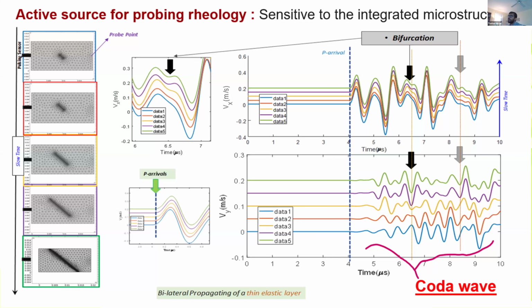So overall, what we're finding is that the active source is really sensitive to the microstructure. It has the potential to being able to actually predict a lot of the stress state, the bulk rheological state of the sample, because it's sensitive to the damage, which is correlated with a certain type of stress strain conditions. And it's by picking up essentially those correlations that the active waveform potentially has information on being able to say something about the stress state and the rheological state of the sample.